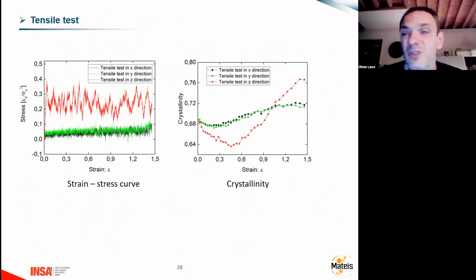So now the mechanical properties, which are again difficult to interpret, but in the directions here in green and black, we have the tensile test parallel to the lamella, and we have very weak properties due to the fact that the lamella are very, very weak, as I said before. So we didn't change that at the moment. And in the Z direction, the mechanical properties are much higher because the amorphous phase plays a significant role. So this is the red curve we have to interpret. Finally, it's not so easy, but okay, this is our result. And here the units are, again, Lennard-Jones units, so it's not easy to compare to reality, but I can discuss that after.